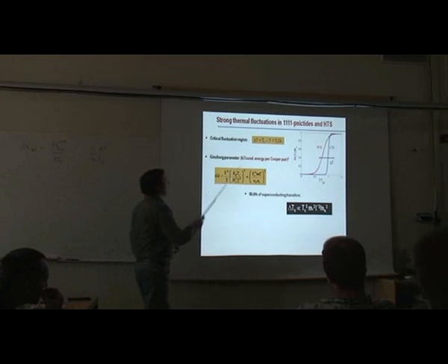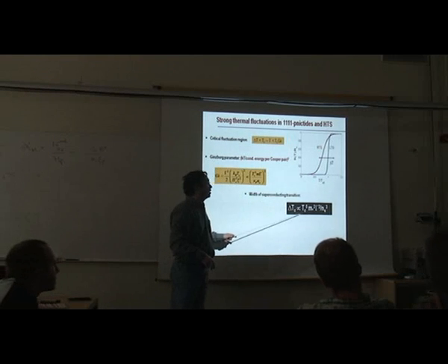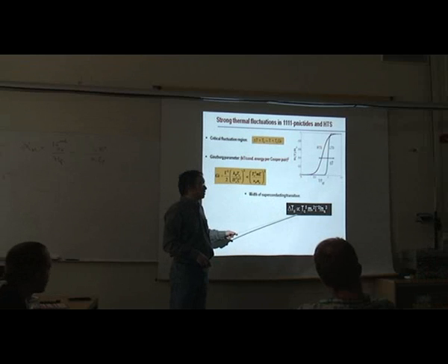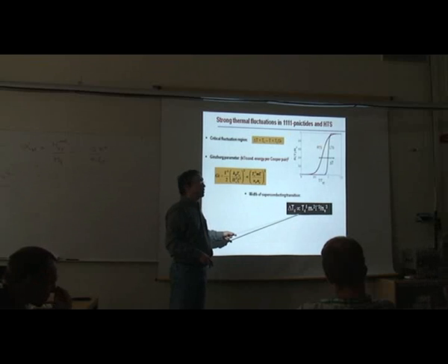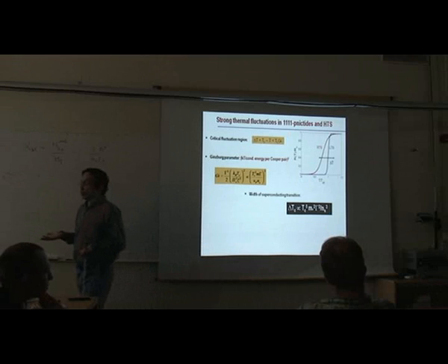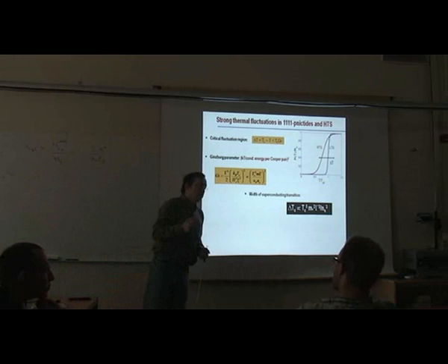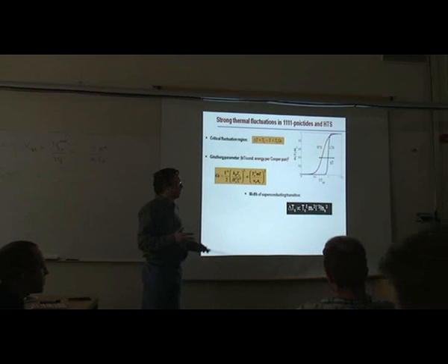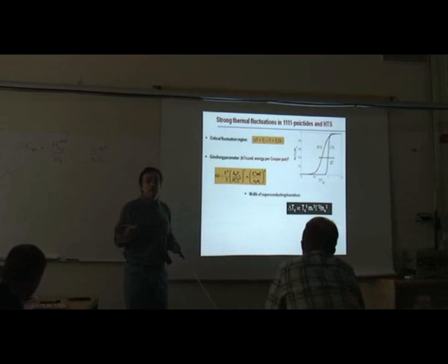Now, if you plug in all these numbers, you can see that there's very strong dependence of this width on Tc. It's Tc to the fifth. Then it's inversely proportional to the carrier density. Now, if we simply double Tc from 20 Kelvin to 40 Kelvin, well, delta Tc increases by a factor of 30. So that explains why low temperature members of the pnictides family behave like conventional superconductors, whereas high Tc members with Tc about 50 Kelvin behave more like cuprates. It's because of this. So we need to know the mechanism.